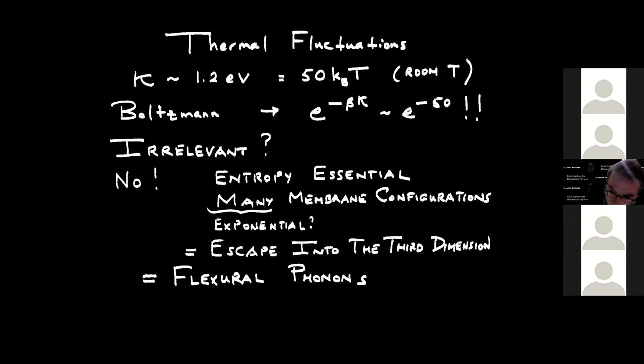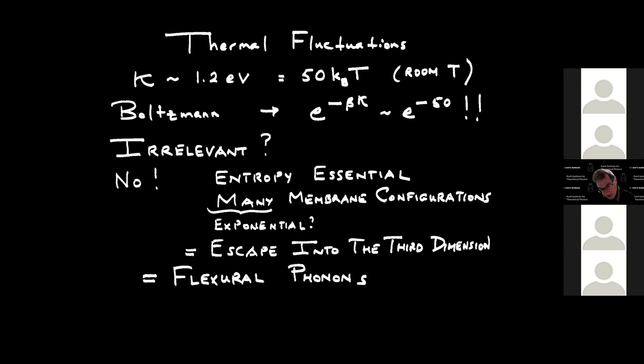This is a system where entropy is essential. It can adopt all kinds of rough topographic configurations, and the density of states can compensate this exponentially small Boltzmann factor. This is associated with all the shapes the system can assume — the escape into the third dimension, which you can think of as another kind of phonon. Besides the two-dimensional phonons, you have this third degree of freedom that costs strain energy and appears in both the bending energy and the stretching energy, so they are anomalously coupled.